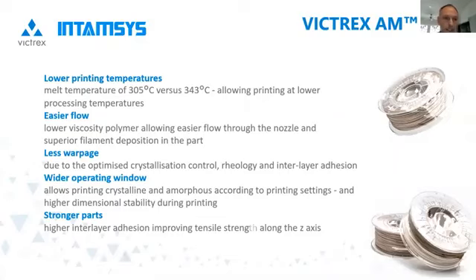So in summary, then, Victrex AM200 is a new PAEK. It's specifically engineered for 3D printing. Its lower melt temperature means that high-performance polymers become more accessible. Earlier, you saw the rheology and how it flows easier than PEEK or PEK, and how it makes it easier to print. You also saw the slower crystallization, which can help interlayer bonding, which should make it less likely to stress and warp.